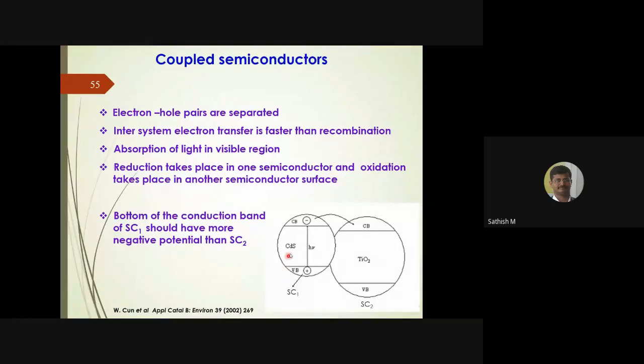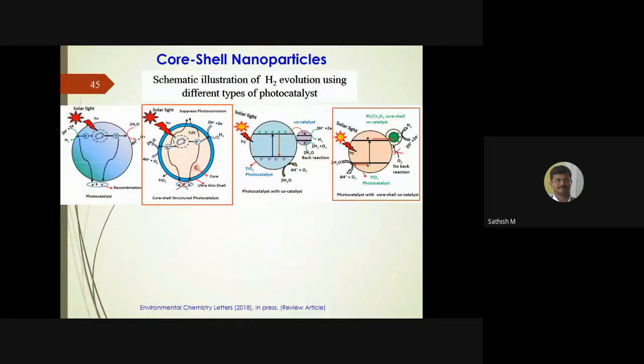So instead of that, very recently, we took a cadmium sulfide core. Over it, we put a very thin layer of TiO2 so that the light can penetrate through this TiO2 layer. The thickness of this TiO2 may be hardly 5 to 10 nanometers.